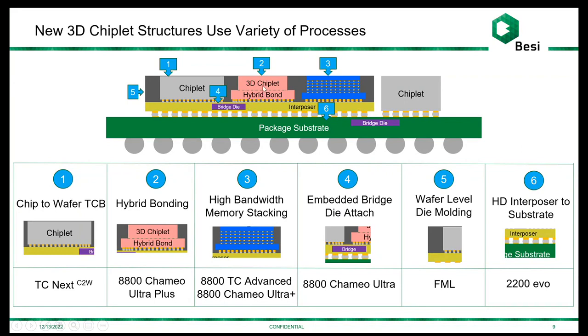But typically you'll have your hybrid bonded chiplets co-located on this interposer with other types of chiplets and other types of 3D stacks of memory or other functions. Could even be optical chiplets, for example. And then these interposers are typically encapsulated, tested, and then further assembled onto a very large package substrate, maybe integrated with other kinds of chips on the side as well. So these things become very complex, and within these structures you have the need for multiple different kinds of interconnects. You have hybrid bonding, you could have chip to wafer TCB for the hybrid bond stack attached to the interposer or the other chiplets, or even for the high bandwidth memory stacking. Hybrid bonding itself can be used in this area as well.